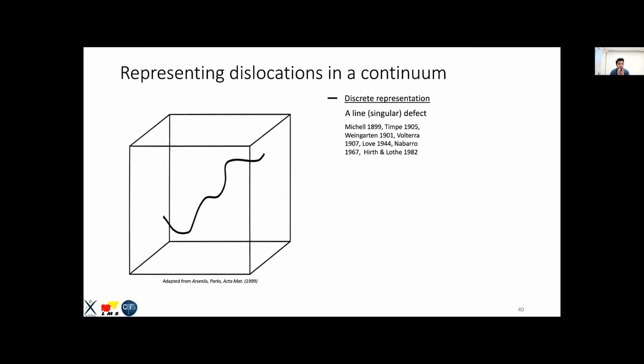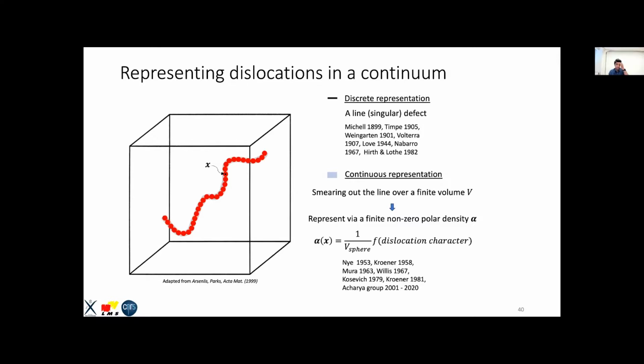Okay, so what do I mean by representing dislocations continuously in a continuum? Most of you would know that one of the most common ways to represent dislocations is as a singular line defect. And this started more than a century ago, from initial works by Michell and Timpe to Volterra to, more recently, Hirth and Lothe and all the people that have done discrete dislocation dynamics after. Another approach is to smear out this dislocation line and this singularity, from an infinite singularity to a finite volume, and then represent the dislocation via a finite non-zero polar dislocation density, which you characterize as follows.